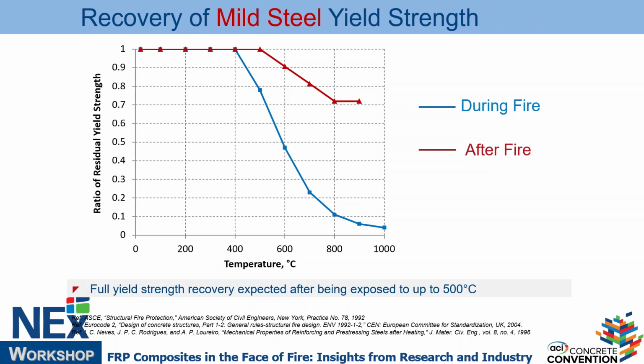Now, good thing is steel recovers part of its properties after fire. I don't know what the new curve in 216 looks like. This is some of the data that I pulled from available references. But you can see that the steel, up to 600, 500 degrees, let's say, after that when it cools down, it gains back its strength, and most of the time it's above 70%. So always in my head I say, if I don't know, worst case I'm going to assume 70% unless we do some testing and verify the capacity, right?